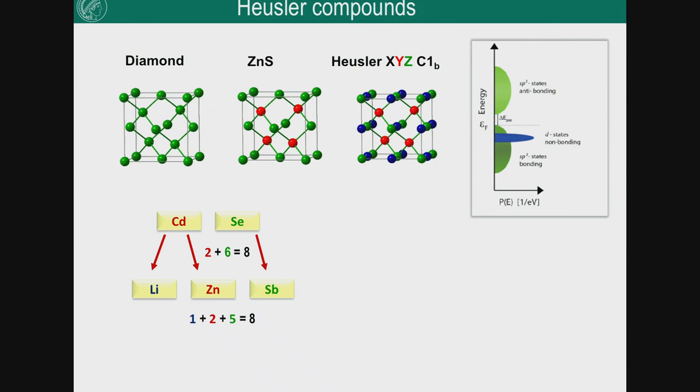so as I said, when it was clear we don't find a topological insulator in an element, one thought about two elements and ended up with mercury telluride. But if you have two elements, you can also take three elements and you have even more fun, okay? So by, for example, filling not only the tetrahedral sites, you can fill the octahedral sites plus half of the tetrahedral sites. And this is the so-called half-Heusler structure, which is also interesting in many regards for topological properties.